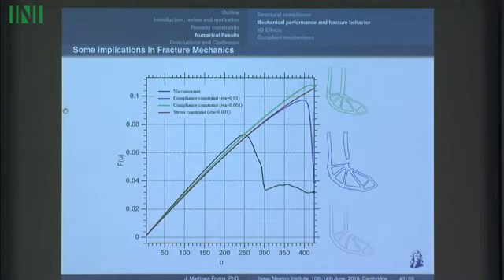Well, these conclusions can be seen if we represent the force versus the displacement. So we see here that for the design that we obtain without the porosity constraint, we have a fracture here, and there is a remaining stiffness in the design because the design, after this fracture, still has some stiffness, so the curve cannot get to zero, so it stays here. And next we have a fracture for the blue curve and for the green. So these two are the two designs that take into account the porosity constraint for compliance.